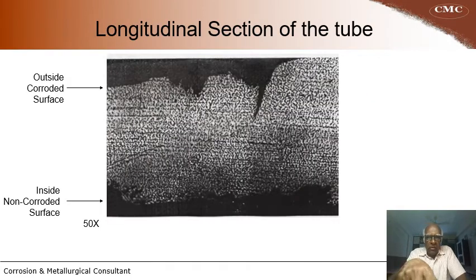This shows the longitudinal cross section of one of the leaked tubes. The outside corroded surface, you can see very rough corroded region, whereas on the inside surface you can see relatively corrosion free, somewhat smooth surface. So this inside surface is exposed to the gas, the outside surface is exposed to the boiling water. So this phenomenon of corrosion has led to the leakage.